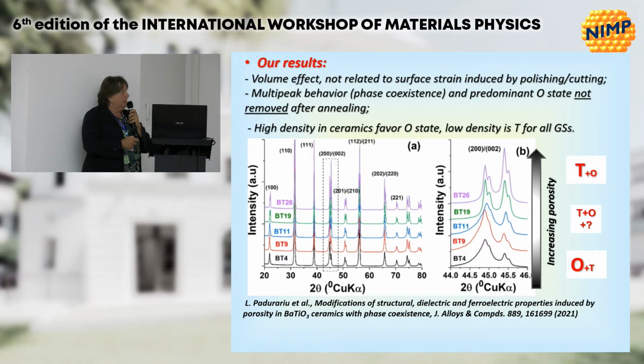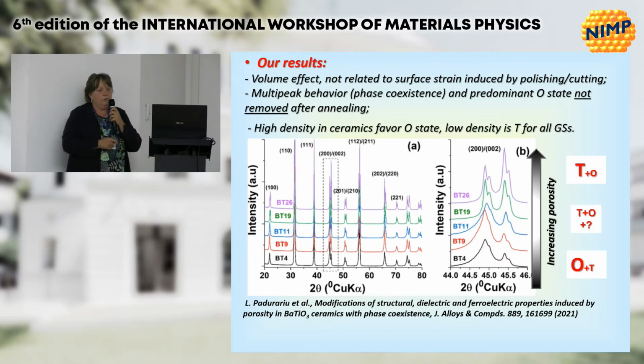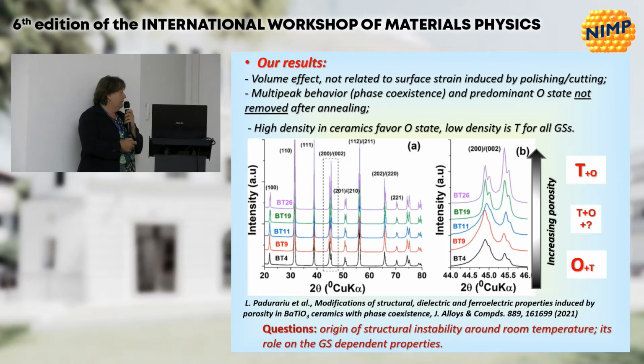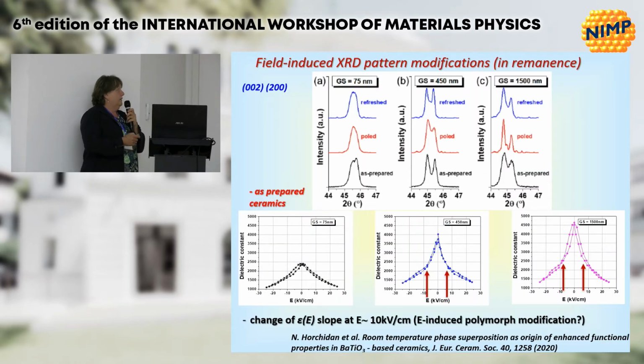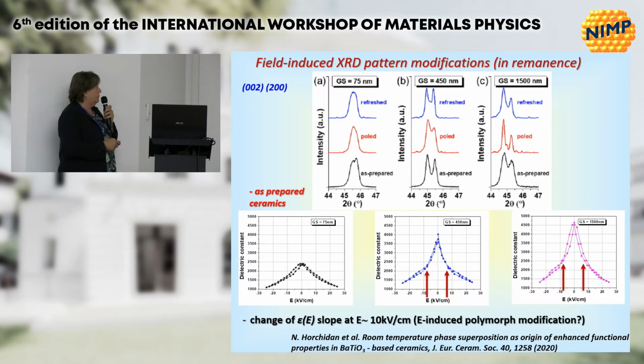So the classical idea that barium titanate is tetragonal maybe should be reconsidered, because when we looked at the literature, we discovered that many papers that report the tetragonal phase have inverted peaks, like here, and not as should be for tetragonal ones. And even ourselves, in a paper studying grain size effects, we found again inverted peaks, but we didn't even look because it was splitting. We said that it's tetragonal and that's it. So the conclusion is that one should always check these effects.